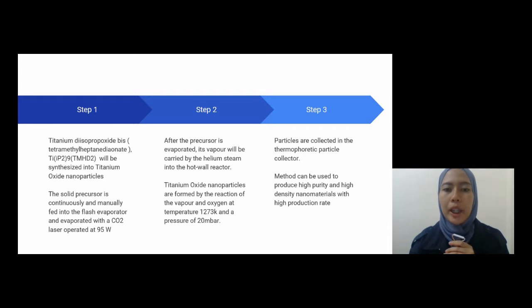Step 2: after the precursor is evaporated, its vapor will be carried by the helium stream into the hot wall reactor. The titanium oxide nanoparticles are formed by the reaction of the vapor and oxygen at a temperature of 1273 Kelvin and a pressure of 20 mbar. The final step is that particles are collected in the thermophoretic particle collector. The method can be used to produce high purity and high density nanomaterial with a high production rate.